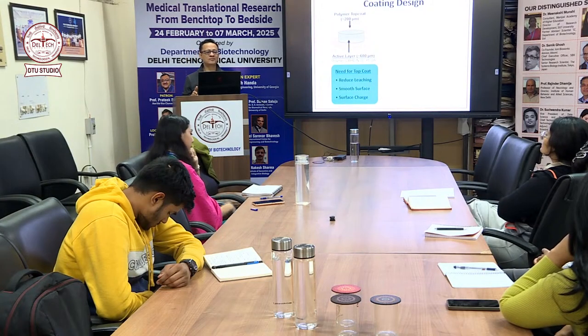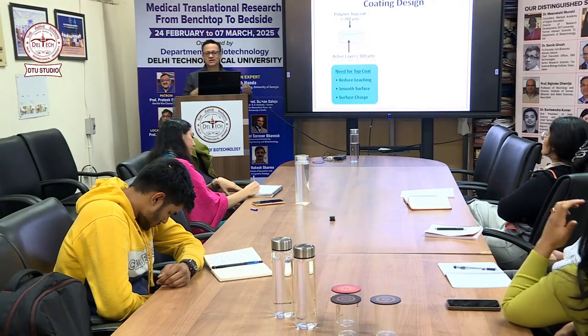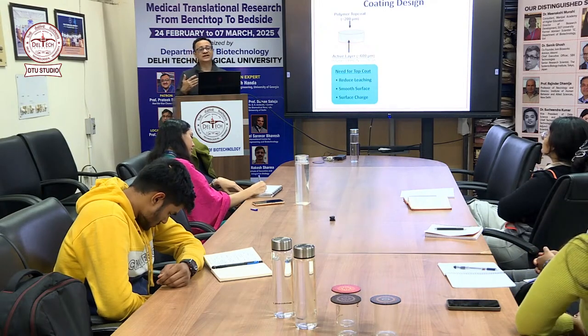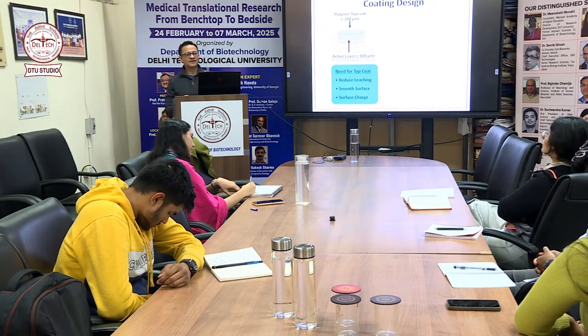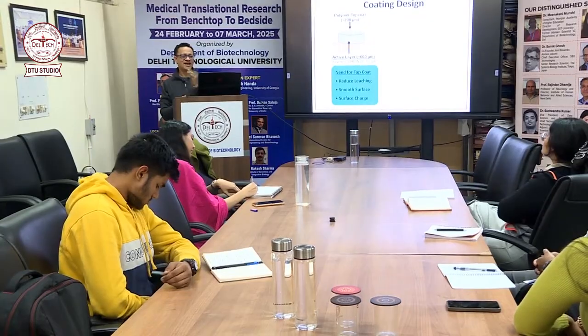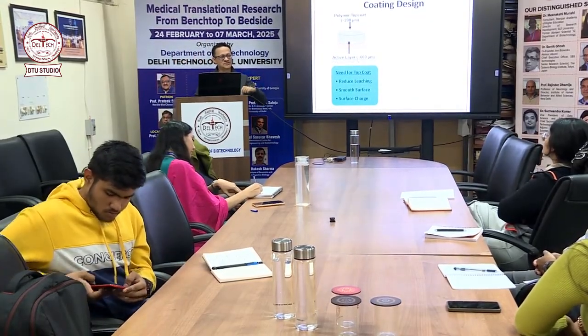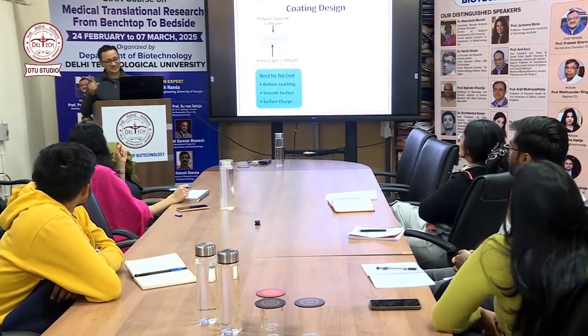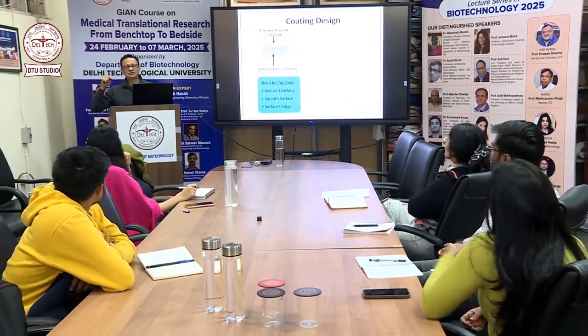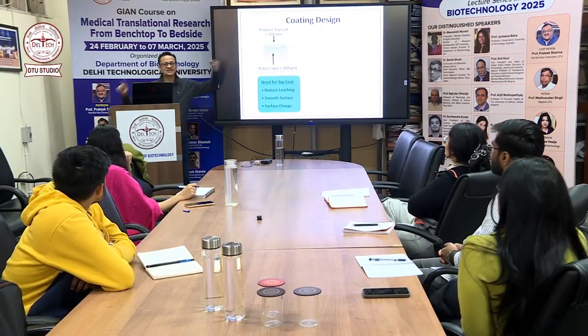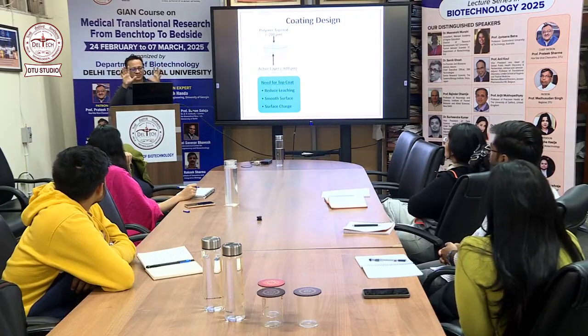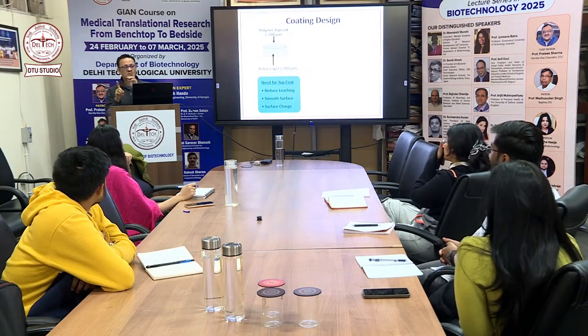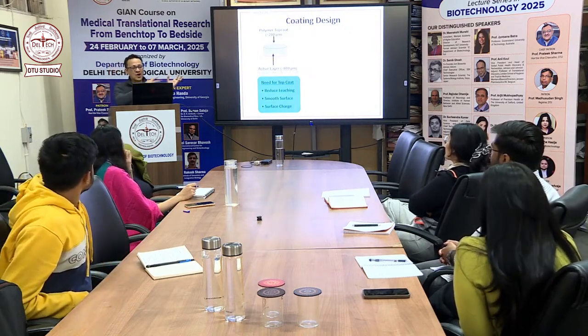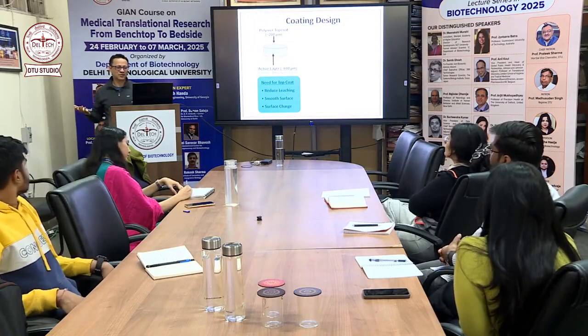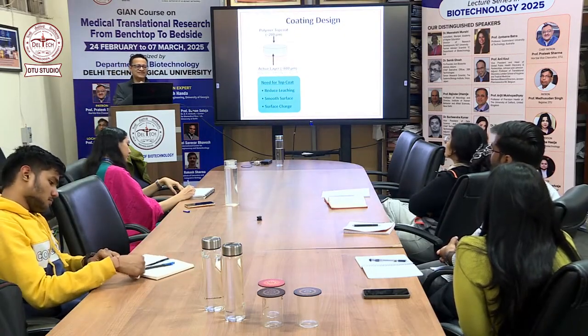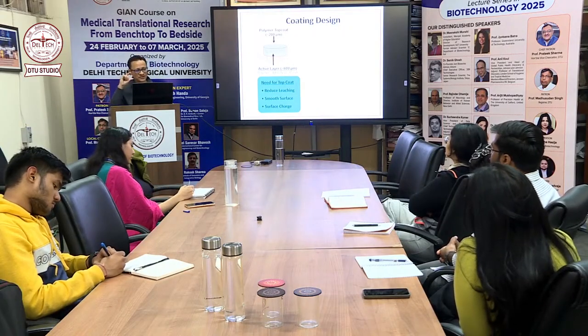What else? Very good. So we want to think, what should our base polymer be? Like, should we use PVC? Should we use polyurethane? If polyurethane, what type of polyurethane? So different polymers have different water uptake. And in this type of application, water uptake is very important. Why? If it's hydrophobic, that's an issue because water is not penetrating inside. Until water goes inside, this coating won't start breaking or releasing. So we want it to be a little hydrophilic. But if it's too hydrophilic, that's a problem. All the NO donor might leach out of the coating. So we want a balance of how much water uptake there is. So we have to decide the polymer.